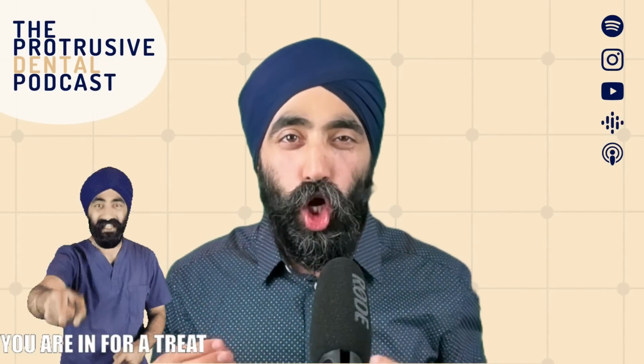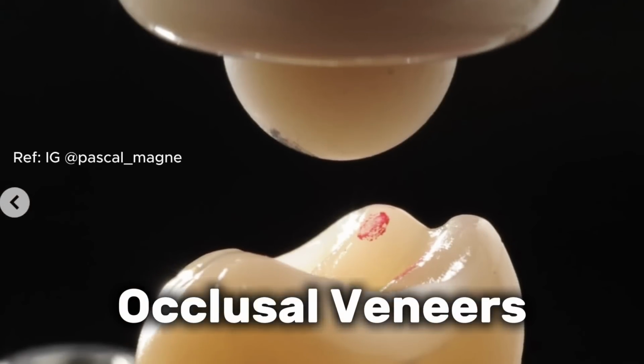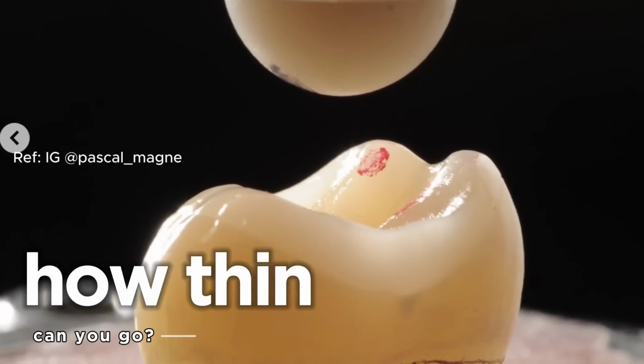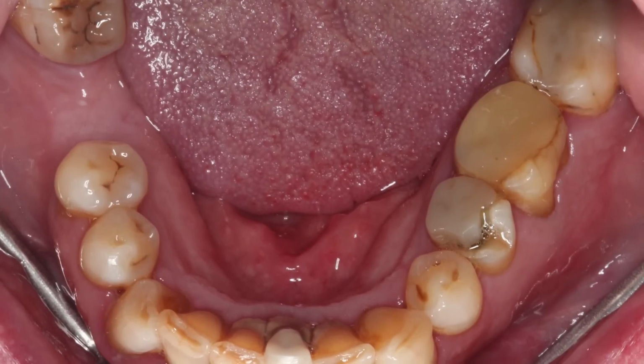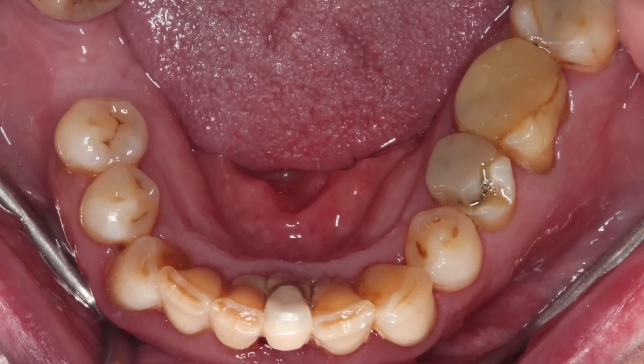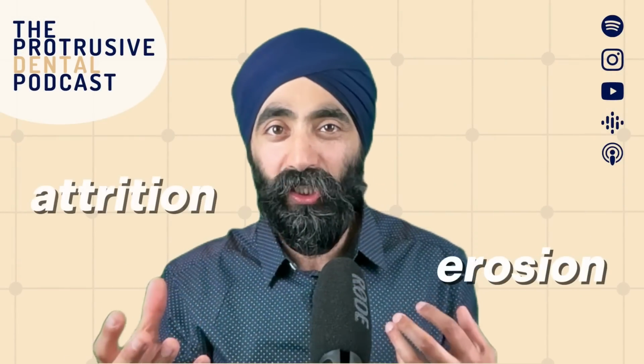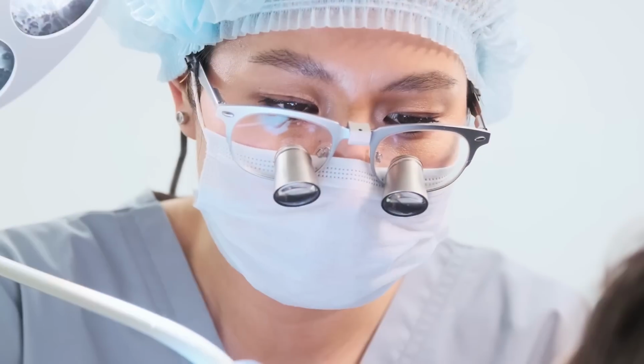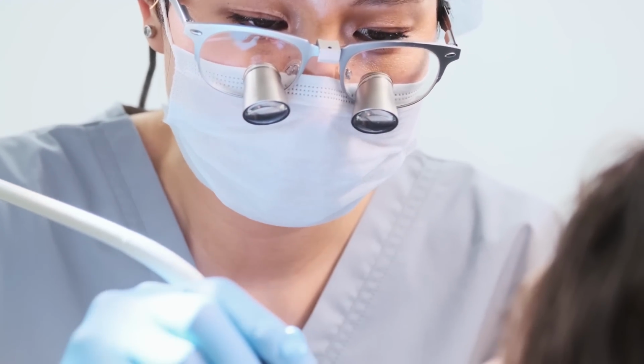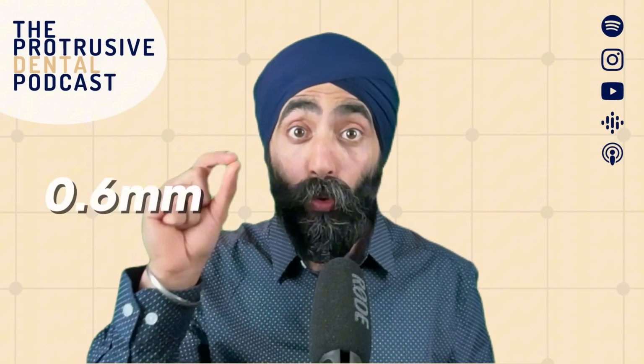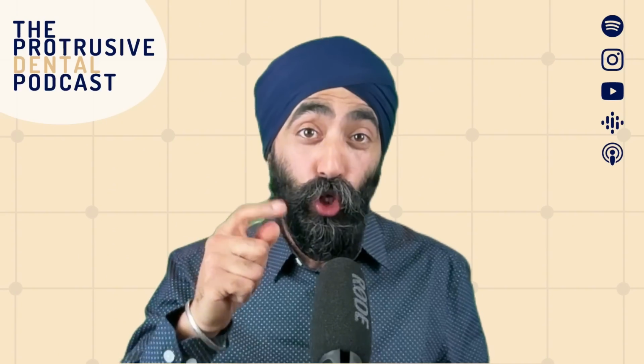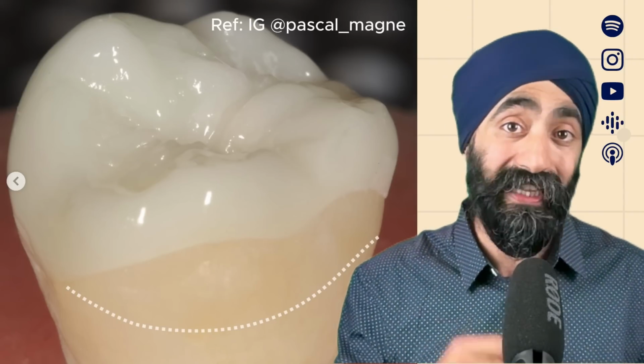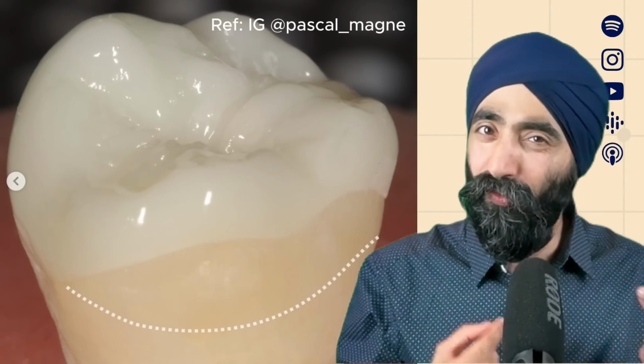We're talking about occlusal veneers. How thin can you go? Think of a lower molar that is worn into dentine, possibly because of erosion and attrition, and you don't have much space and you don't really want to prep so much. We can go as thin as, let's say, 0.6 millimeters. And what if I told you you can do it in indirect composite? And that's probably, in many cases, the preferred choice.